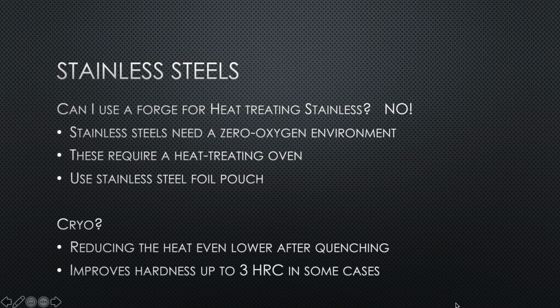This may improve hardness, sometimes up to 3 HRC, depending on the steel and how it's done. Obviously, liquid nitrogen is really, really cold. You'll get two-thirds of the way there with dry ice, and you can do it in your home freezer. Despite what people say, you will get some effect from a freezer, but it's questionable.